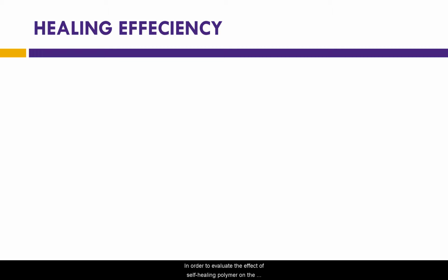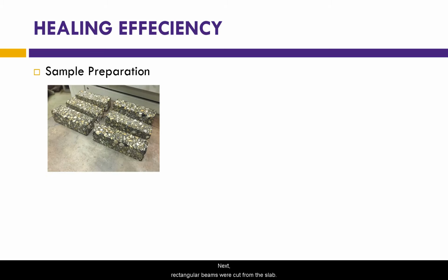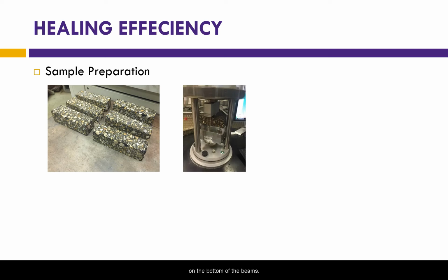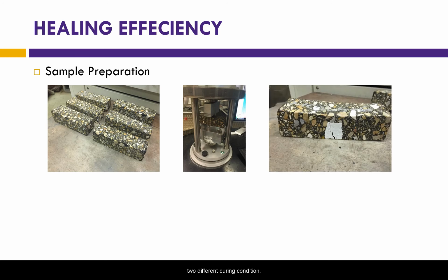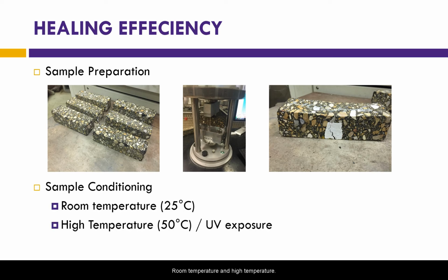In order to evaluate the effect of self-healing polymer on the self-healing performance of asphalt mixtures, slabs are compacted using the polymer modified binder. Next, rectangular beams were cut from the slab. Using a 3-point bending setup, cracks are induced on the bottom of the beams. After creating the crack, samples are placed under two different curing conditions, room temperature and high temperature. For samples containing UV light activated self-healing polymer, the high temperature curing condition was replaced with UV light exposure.